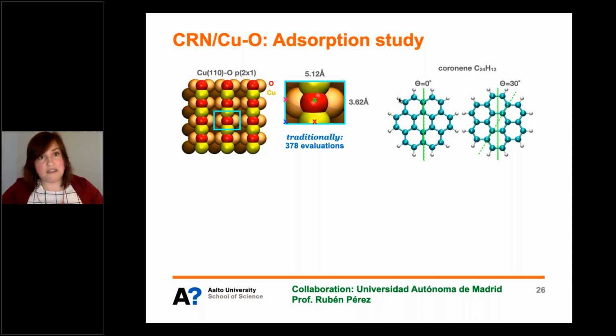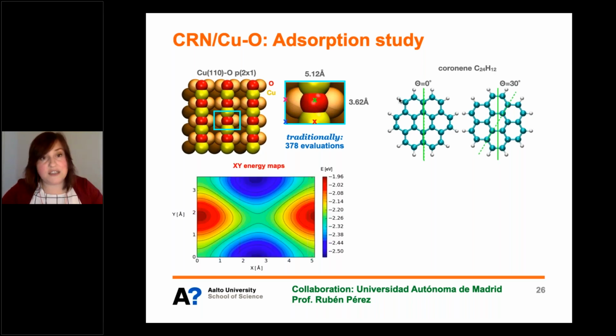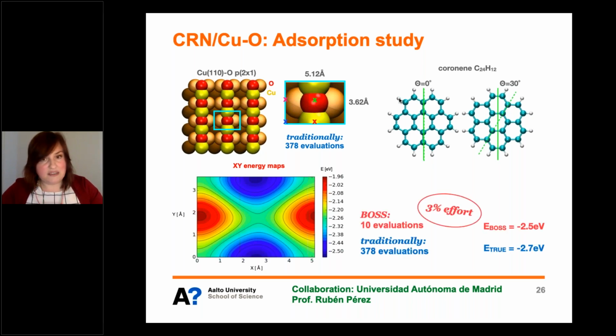So then we thought, okay, this looks easy for building blocks. Can we put this into BOSS? And we did. We found this XY energy map, and indeed copper was the adsorption site. And the best thing is that this was found in about 10 evaluations, so about 3% of the effort that Diego did. And the energies are very close, minus 2.5, and this difference comes from the fact that coronene is slightly deforming when you relax everything. So this was a very good result.